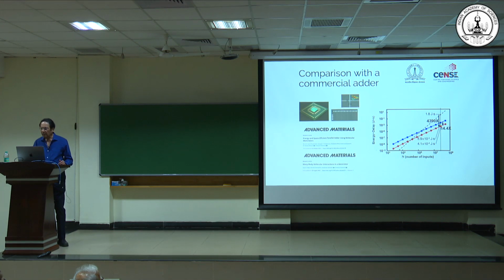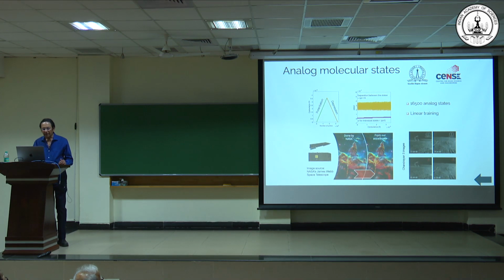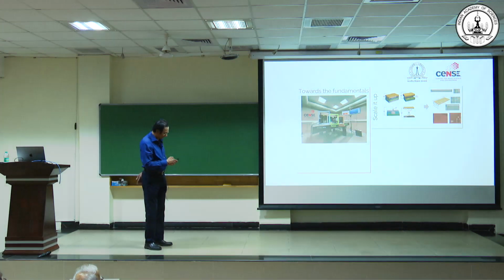But what was even more remarkable is the most recent work that Sritosh published in Nature, which is a device which produces 16,500 analog states, achieved just by pulsing the circuit. You can attain different value settings of these things. Using this, he created a crossbar switch, and that crossbar memory was able to do a Fourier transform processing of NASA data, which is frequency data, and convert that into an image.